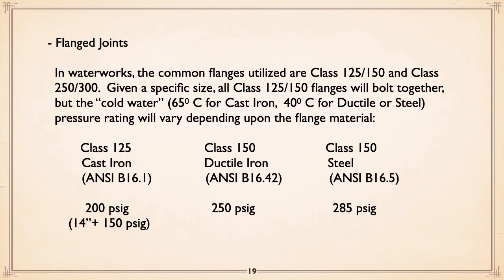Flange joints. In waterworks, common flange sizes are class 125/150 and 250/300. Now, at a specific size, say 6 inch or whatever, all 125, 150 flanges will bolt together. But the cold water rating, cold being 65 degrees C for cast iron, 40 degrees C for ductile or steel, the pressure ratings will vary depending on the flange material. Here's how it works. You've got a class 125, which is cast iron. There's actually 3 different standards, one for cast iron, one for ductile, one for steel.